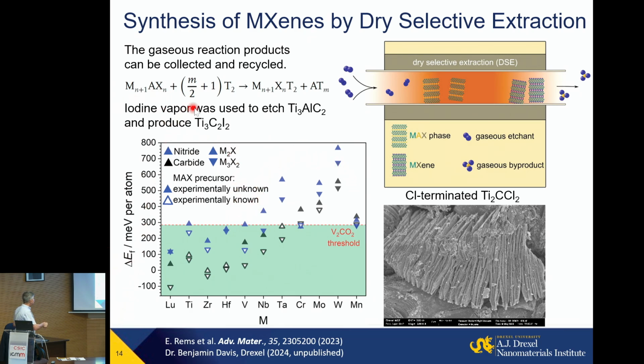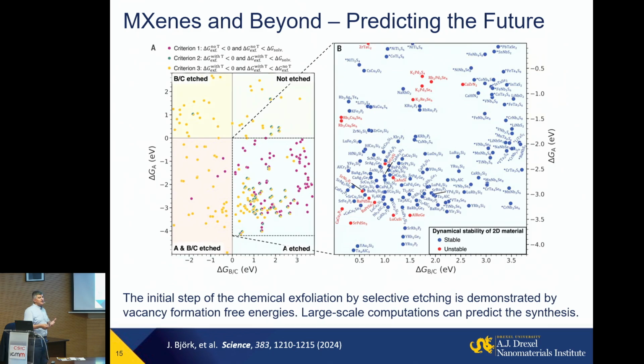We showed also recently that we can make, by gaseous etching, something we used to make carbide-derived carbon, removing just both metals, iodine and chlorine terminated materials, just without any washing, any water, because molten salt you have to remove by washing, sometimes changing termination and so on. And of course, the sky is the limit here. I'm referring again to a paper from a Linköping group, published in Science in March, I believe, this year. They predicted, for example, two-dimensional silicides by selective etching and demonstrated it on ruthenium silicide with oxygen termination. Definitely many more materials in other inorganic transition metal systems can be made and discovered from layered structures by this type of selective etching technique.